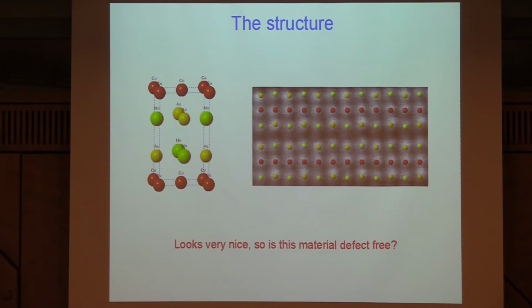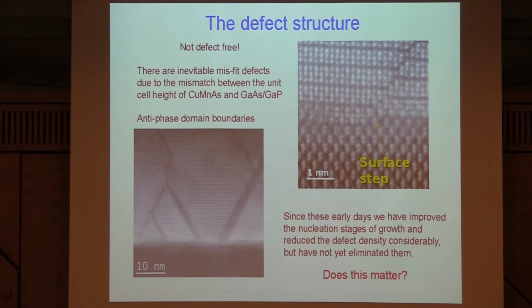So the question is, is the material defect-free? Nah. No, it's not. In fact, it's very difficult for it to be defect-free. You see, we're growing a tetragonal structure on a cubic substrate. So the step height of the cubic substrate and the step height of the tetragonal are not the same. They can't be. And inevitably, the material has to correct for that somehow, okay? Either by some distortion or some local strain at the interface, or by simply creating a defect. There's two ways it can do it.